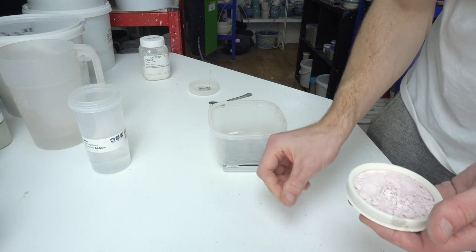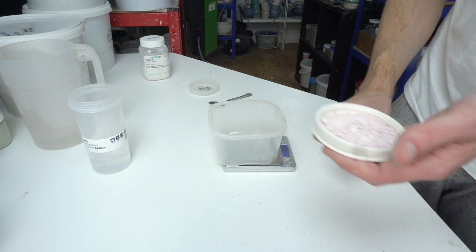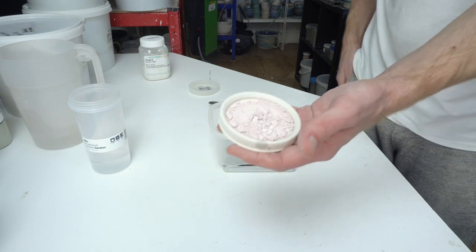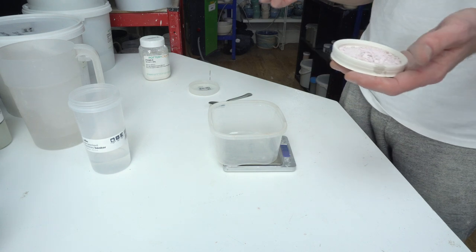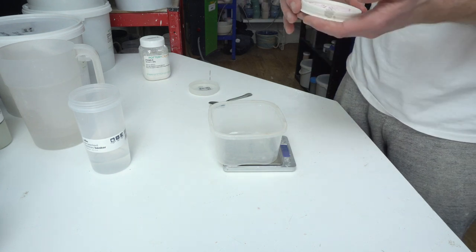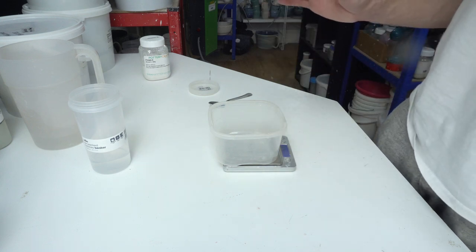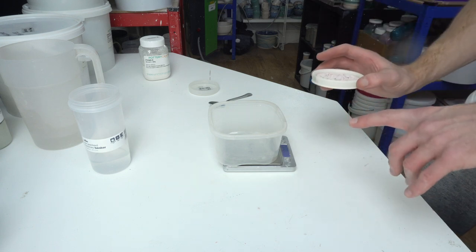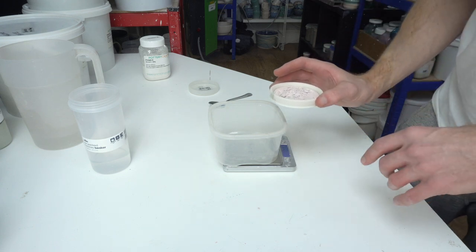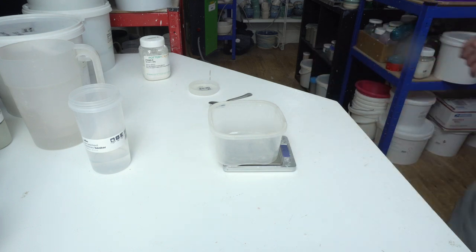And so that's how you can tell you've done it right. If they become glassy, you've gone too far, they'll probably all fuse together, you won't be able to break them up. But if they're still matte, but not capable of dissolving in water, you've got it right. And yeah, the chemistry is quite simple, but you need to understand the overall chemistry to get it right. So I'll do this in fast motion because I'm going to put a mask on, and I'll post the recipe.